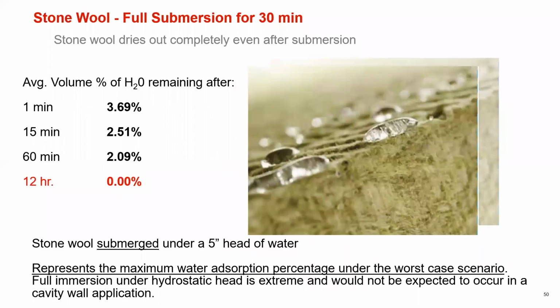One thing that I do want to note is that because trapped air makes up the R value within the insulation, if you were to put this product under a constant head of water, a hydrostatic head of water, it will eventually take on water. The water goes through the gaps in the fibers, so it's not absorbed into the fibers. But what's beneficial here is how quickly the water can drain through. If you saturate a board for 30 minutes, within 12 hours, it's completely void of water.